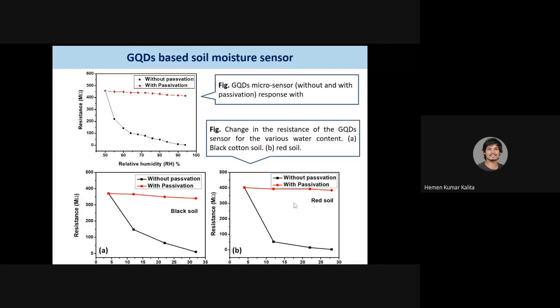That is, there is an increase in the current, that is a decrease in the resistance, with the increase of the water content. Whereas for the passivation, there is no appreciable change in the resistance, which shows that water is the reason for this change in the resistance of the GQD sensor.